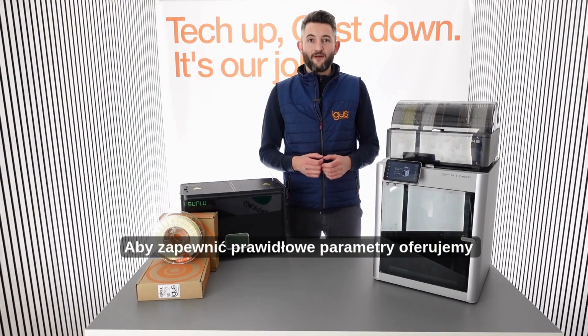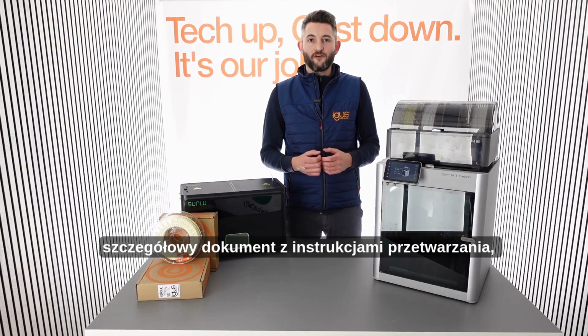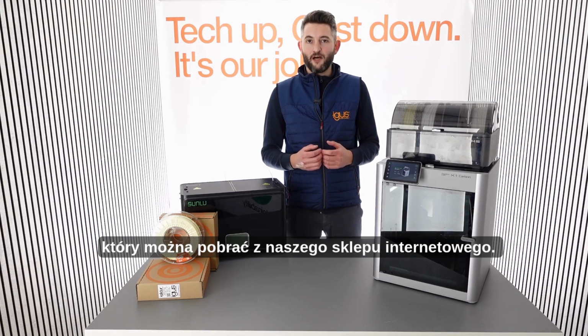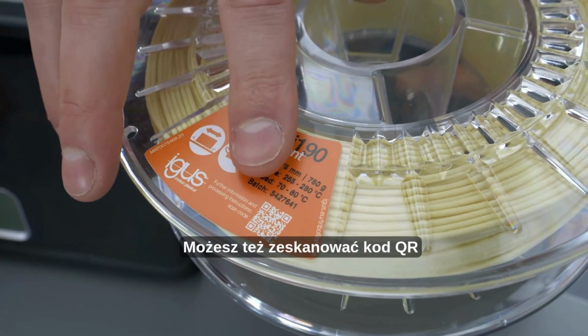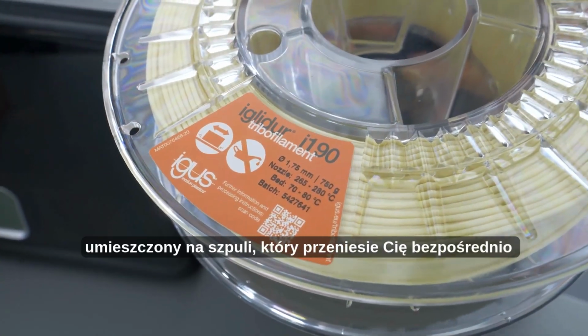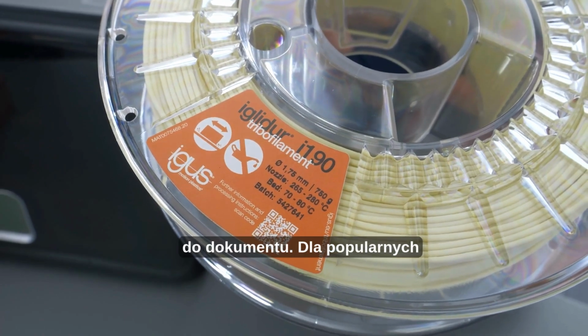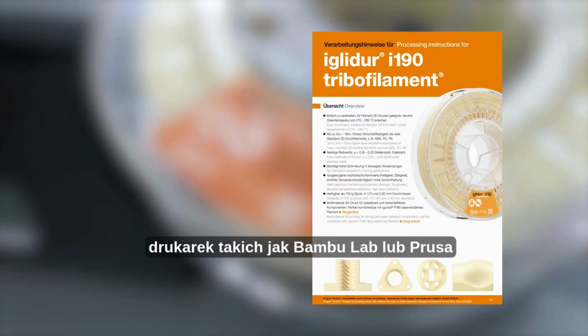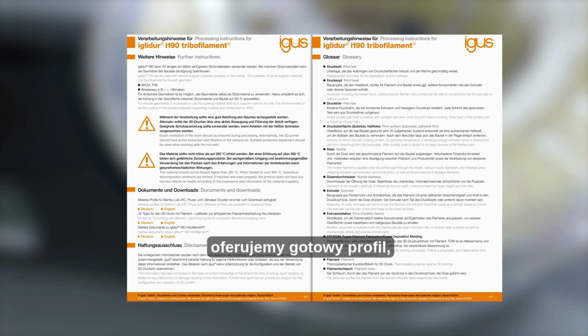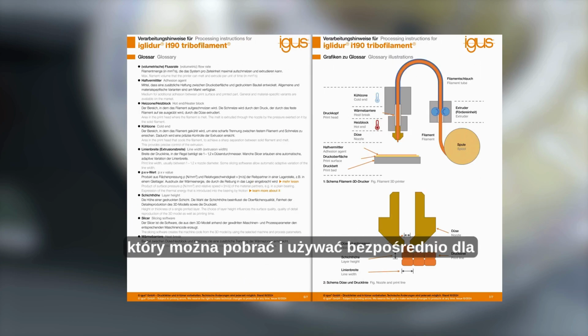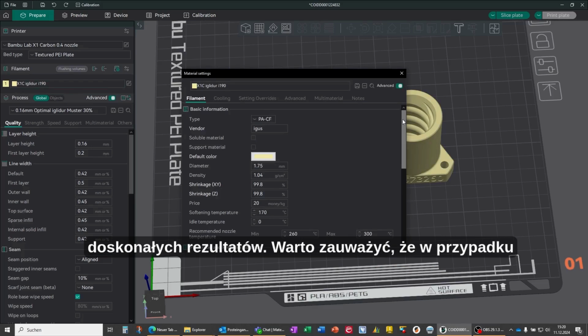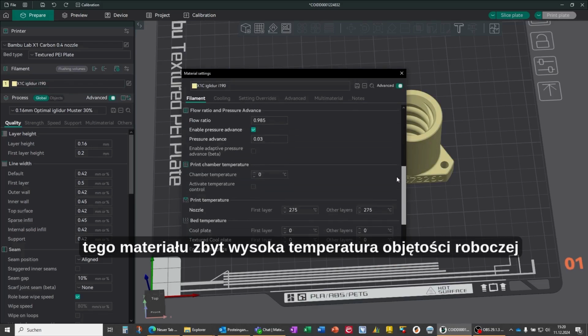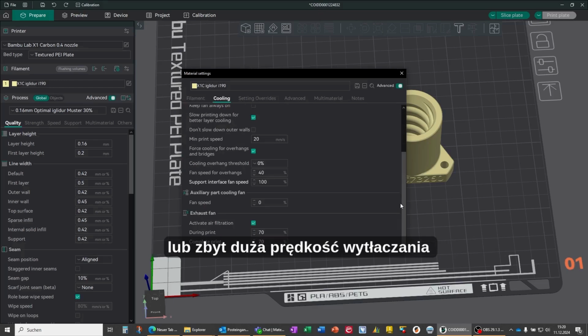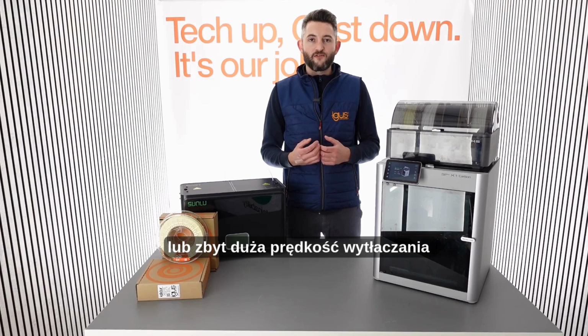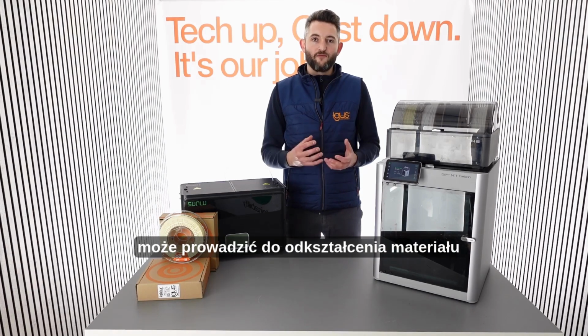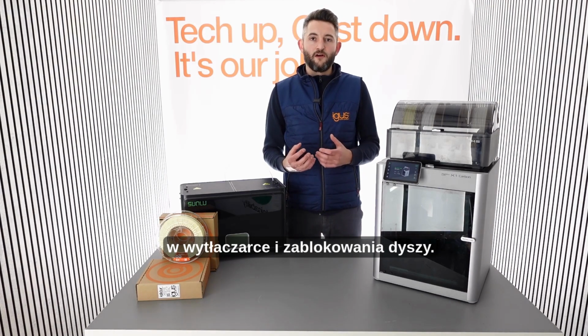For the correct print parameters, we offer a detailed document with processing instructions that can be downloaded from our webshop, or if you scan the QR code on our spool, it will lead you directly to the document. For popular printers, such as the Bambu Lab or the Prusa machines, we offer a ready-made profile that can be downloaded and used directly for great results. I should note for this material that too high of a build volume temperature or too high of an extrusion speed can lead to deformation of the material in the extruder and to blocking of the nozzle.